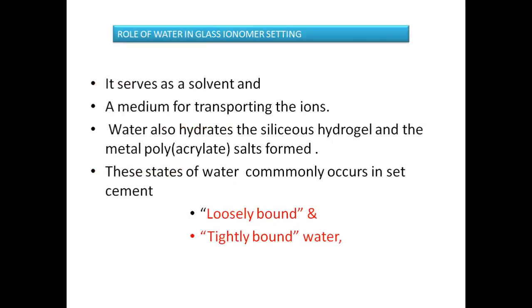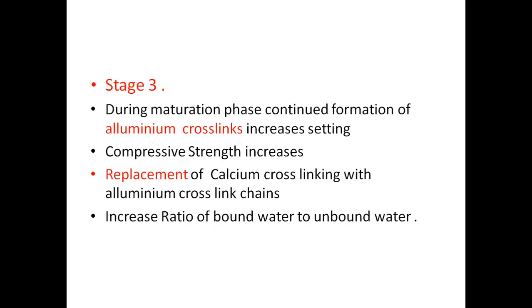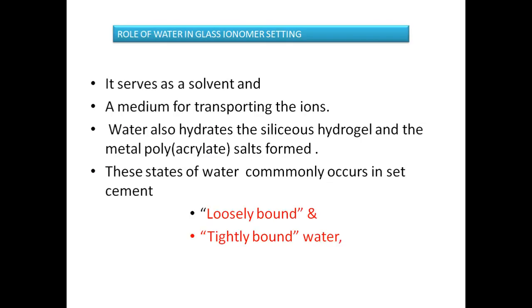Generally, the initial setting time will be around 4 to 5 minutes, and the final setting time will prolong up to 48 hours. The role of water in glass ionomer cement setting is that it acts as a solvent and a medium for transport of ions. There will be two forms of water, the loosely bound and the tightly bound.